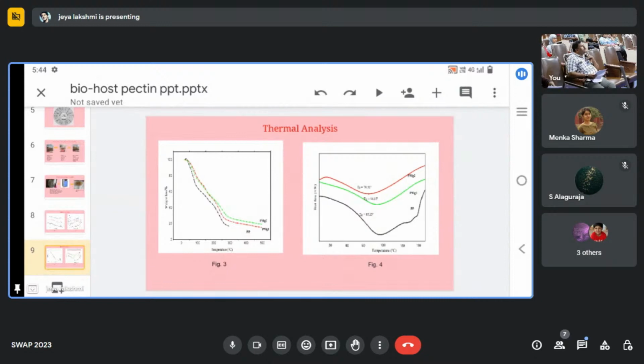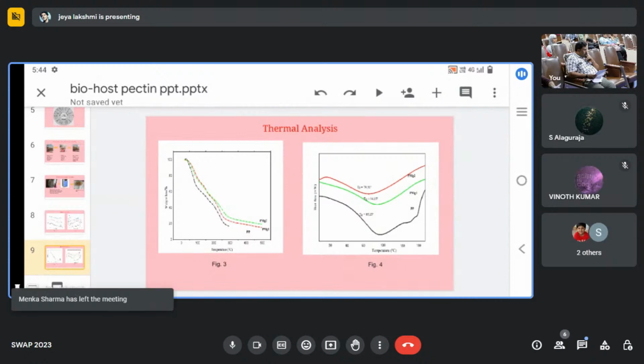And next, we move to the DSC analysis. In DSC analysis, in pure pectin we have a glass transition temperature in the range of 85 degrees. In the next sample, we have a transition temperature of 94.1, which is due to the intermolecular coordination between the oxygen and magnesium cation in the polymeric chain. In the third sample, we have a low glass transition temperature compared to the previous sample, which is 79.56 degrees. This is due to the weakness of the dipole interaction between the polymer chains, and this indicates the flexibility of the polymer chain and the easy flow of ions through the polymer network. From these studies, it reveals that the PMG2 sample has a higher ionic conductivity than the PMG1 sample.